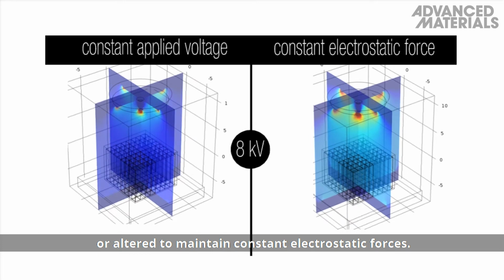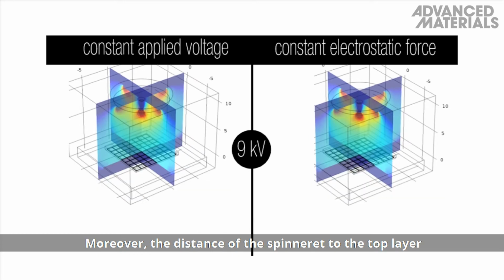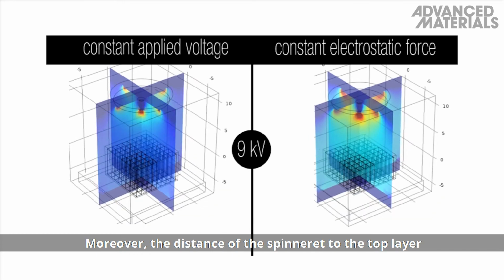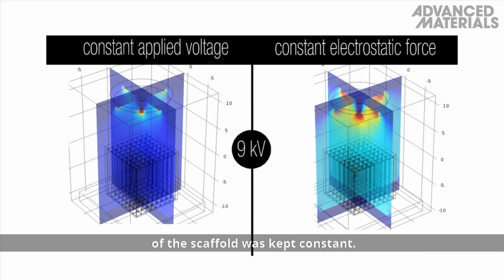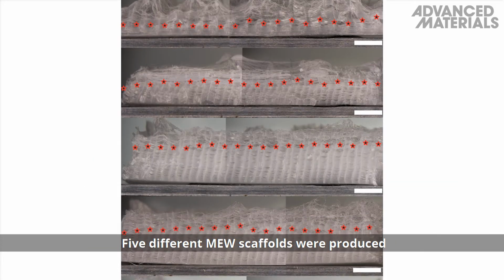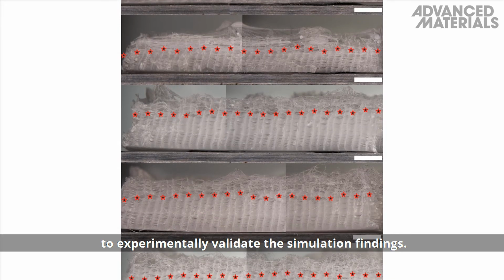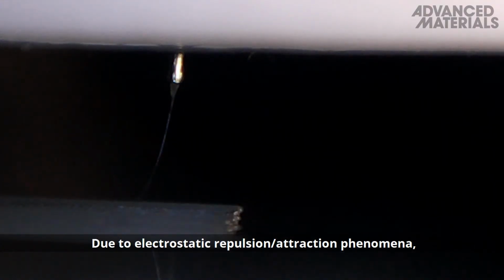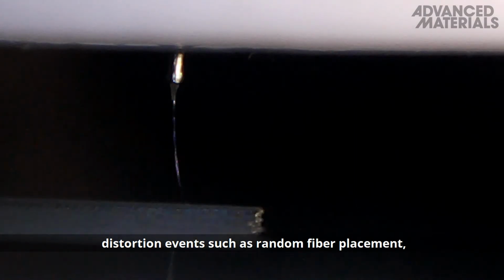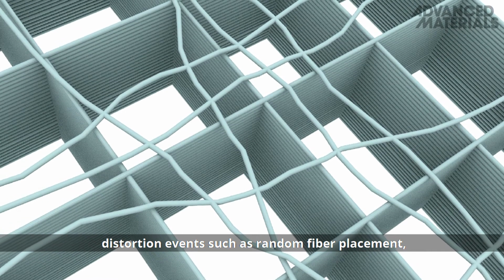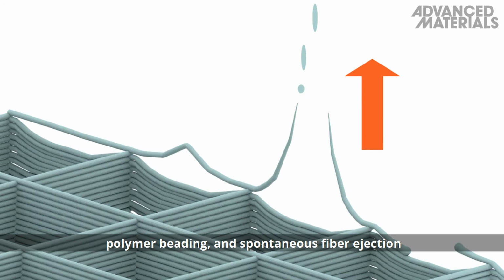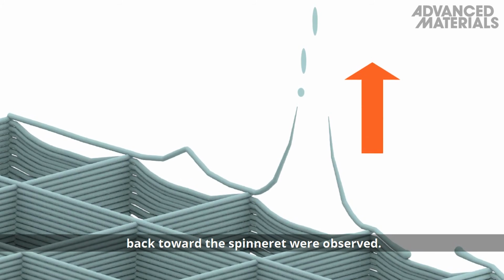to maintain constant electrostatic forces. Moreover, the distance of the spinneret to the top layer of the scaffold was kept constant. Five different MEW scaffolds were produced to experimentally validate the simulation findings. Due to electrostatic repulsion-attraction phenomena, distortion events such as random fiber placement, polymer beading, and spontaneous fiber ejection back toward the spinneret were observed.